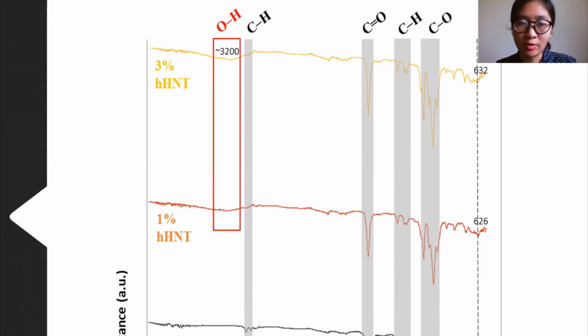It is suggested that the incorporation of a higher concentration of HHNTs affected the strong peak signals at 2995 and 2945 wave numbers originally detected in the PLA spectrum. A band shift was also observed for 1% and 3% PLA HHNT fiber composites at 626 and 632, which are associated with the formation of silicon-oxygen-aluminum bond stretch of halloysite. These findings could be attributed to the bonding interactions between PLA and HHNTs.